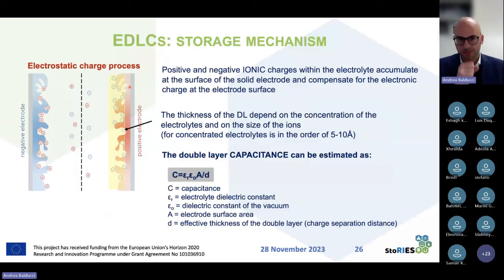Going a little bit into detail, what is important to understand is that when we are storing the charge, we can define this parameter, which is the capacitance. And the capacitance is given by this expression, which is not extremely complicated, so it can be easily analyzed, where we have the dielectric constant of the vacuum and of the electrolyte, so this first part. Then we have the surface area, so the area in which this double layer is taking place. And then this product is divided by the thickness of the double layer.